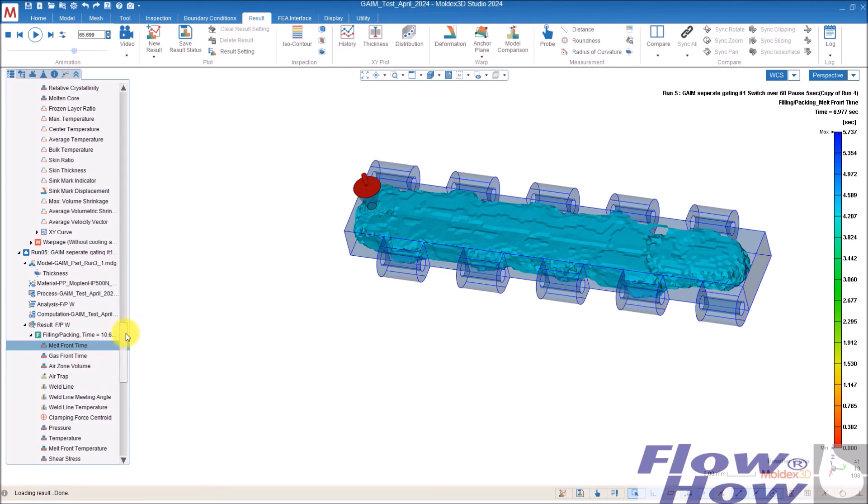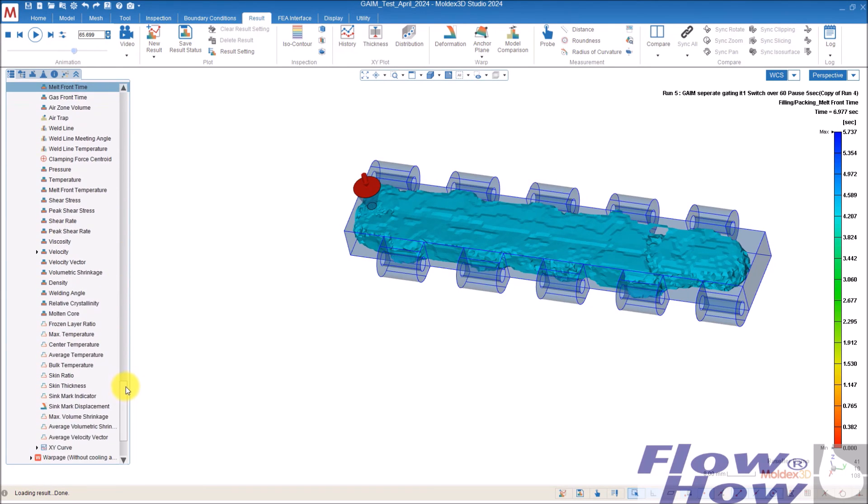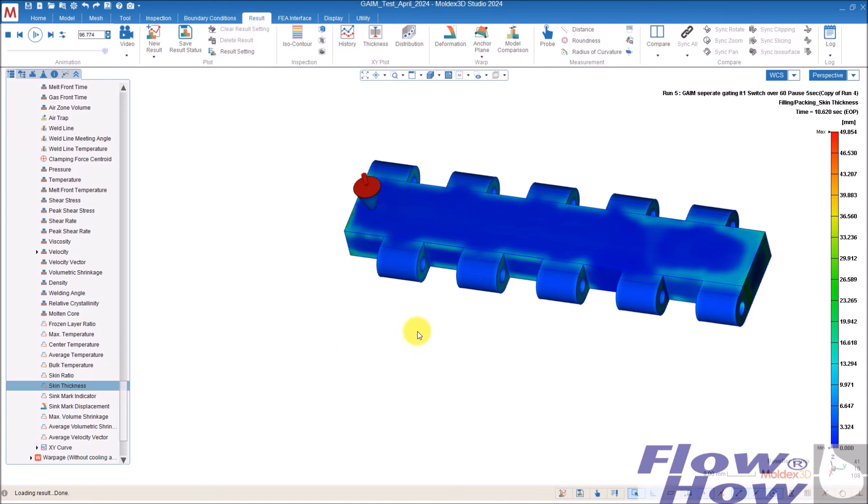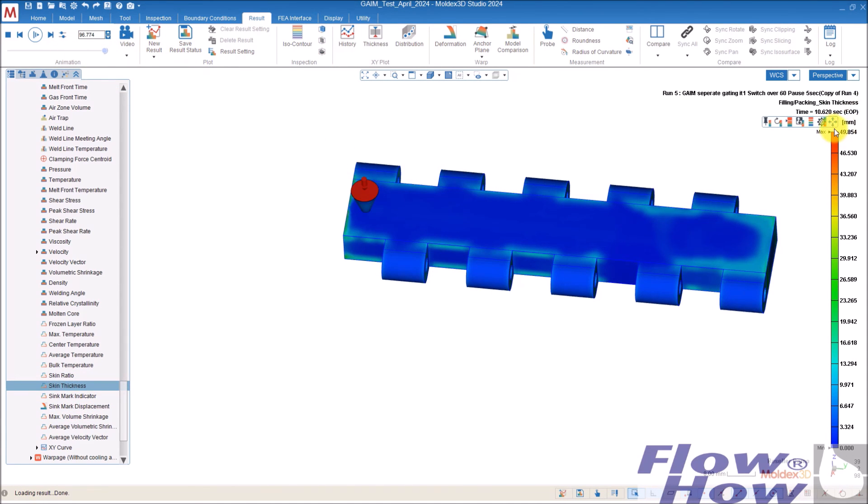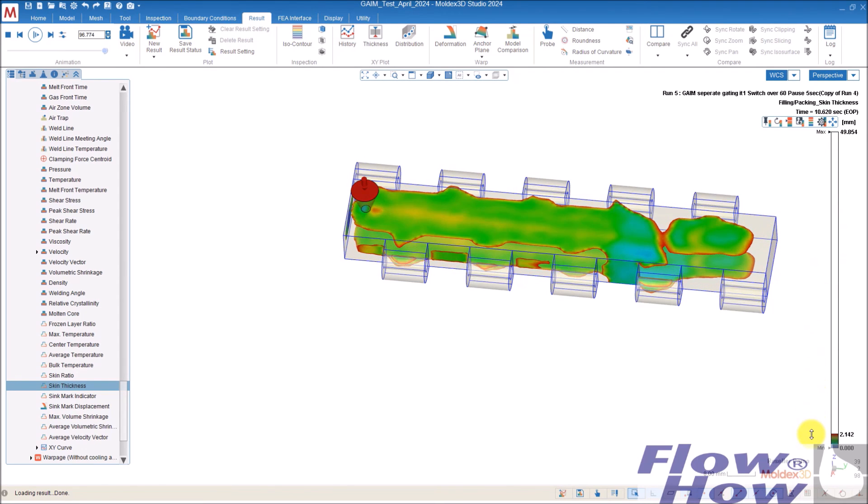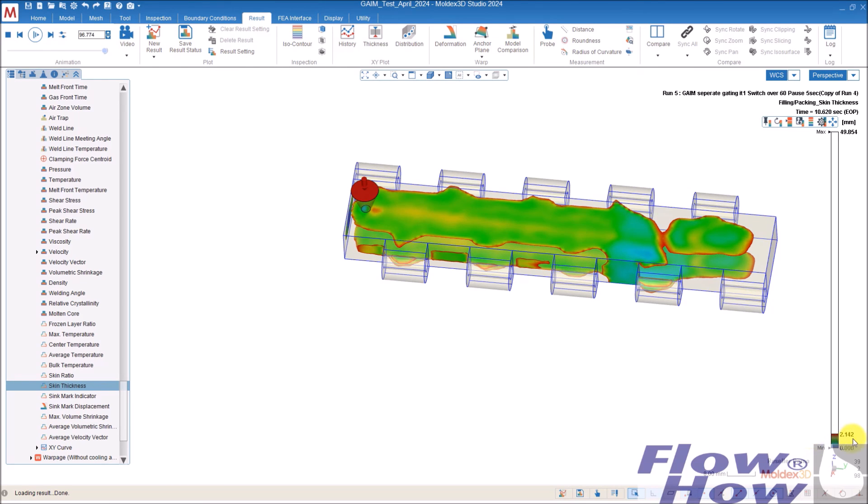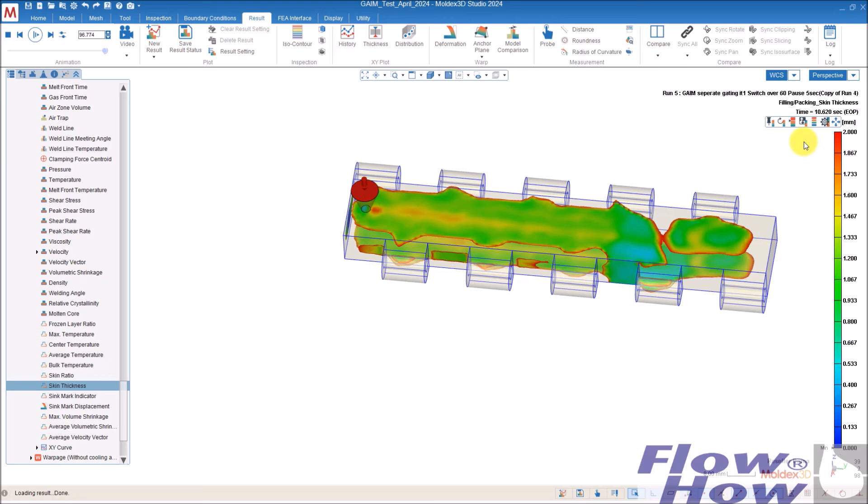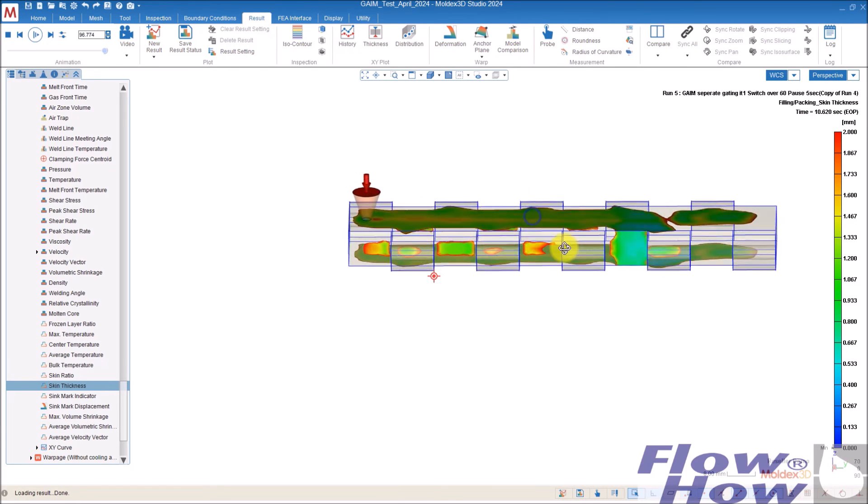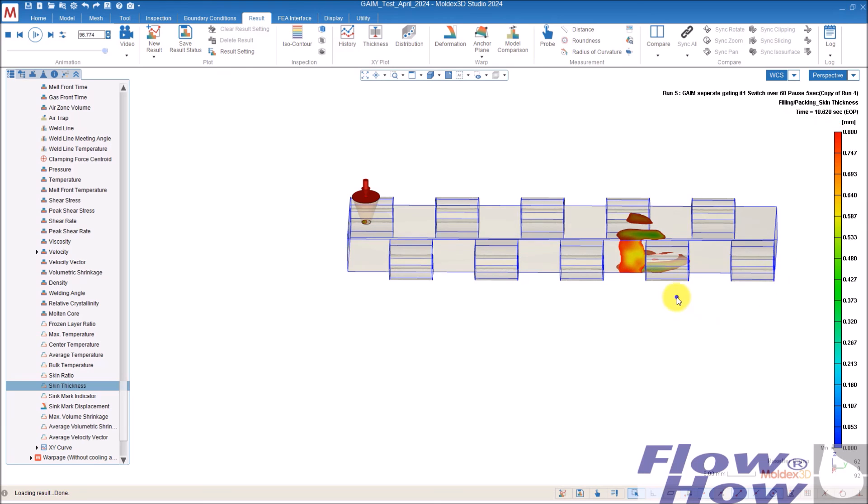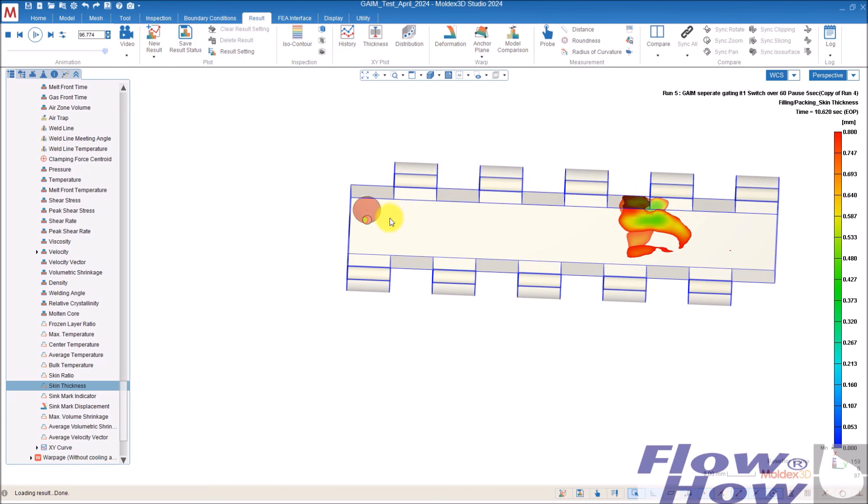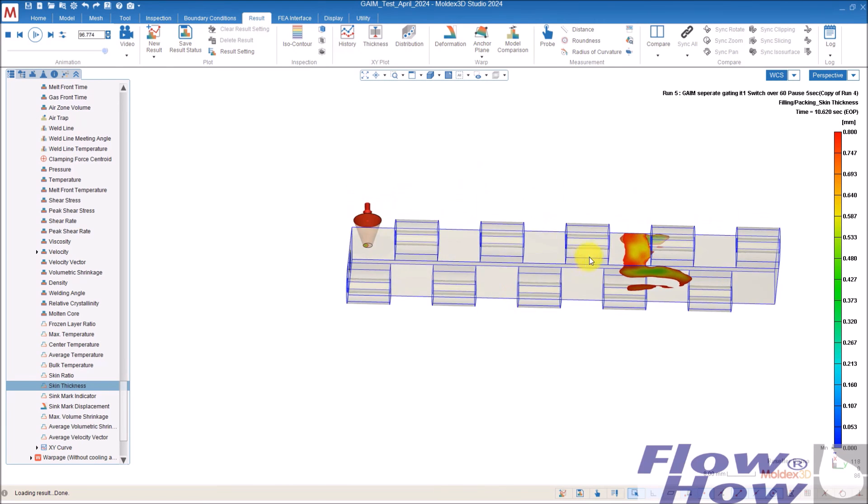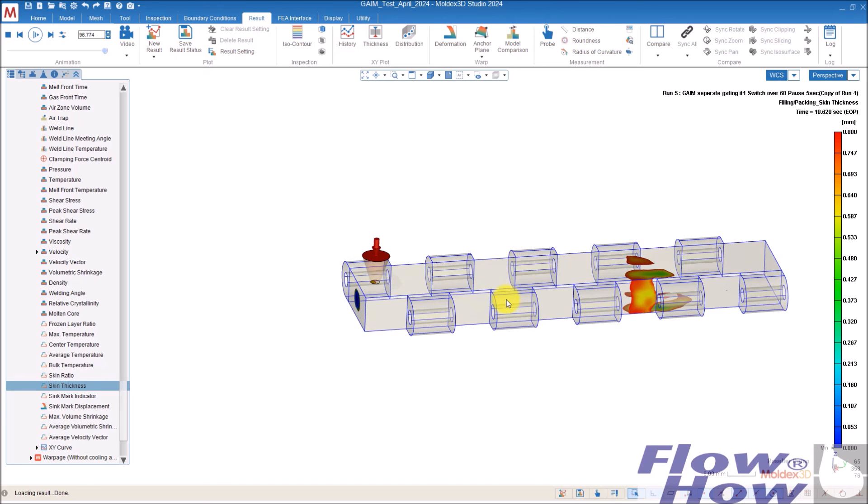You can also look at the skin thickness, which is quite useful. And scale it maybe a bit down and see how uniform it is. Now maximum is two. If I put this for two millimeters, you can see the skin thickness there is two millimeters. But do we have some very thin areas? 0.8. Yeah. Out here. So you can play around with the geometry. You can play around with the process to find the optimum before you invest a lot of money.